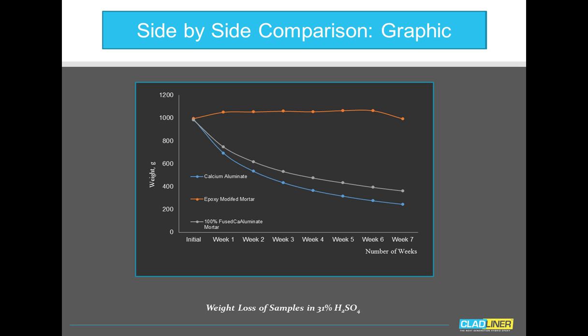We look at those graphically now. We could see here the epoxy modified mortar is the orange line on the top, and the gray and blue represent the calcium aluminate and the pure fused calcium aluminate respectively. And you can see the dramatic difference in the weight loss after the immersion.